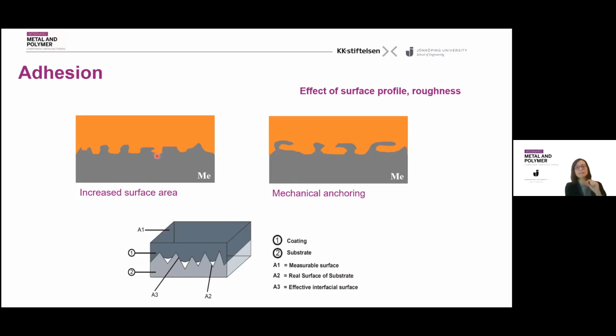We should also be really careful when increasing the roughness of the material, because if the profile between valley and peak is too narrow, maybe the coating material is not able to penetrate the full profile, providing voids and lack of adhesion between the two. So roughening a surface is important, but we should not exaggerate. There is an optimum value after which too much roughness can be counterproductive.